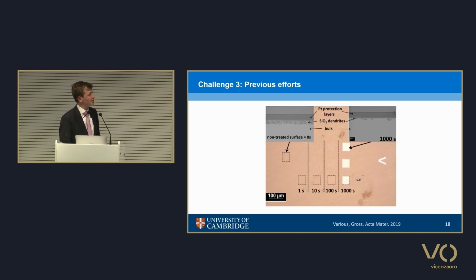And so perhaps the best achievement to date is by Oliver Gross and Nico Neuber. And they were able to take the Schroers alloy shown up here and reduce it down to, sorry, that's not the Schroers alloy, that's their intermediate alloy. And then ultimately they were able to get down to tarnish scales of this value, which you can see are much whiter than they would be otherwise. But unfortunately, they had to use an effect called ion implantation. And that requires a gallium ion beam and is of limited industrial use, largely because wear will remove that surface layer, but also it's very difficult to do that on non-flat surfaces.